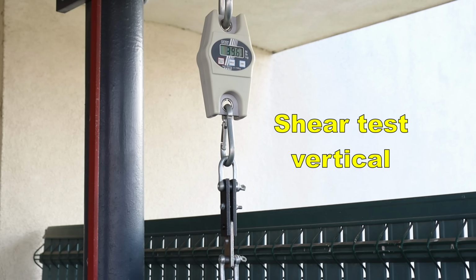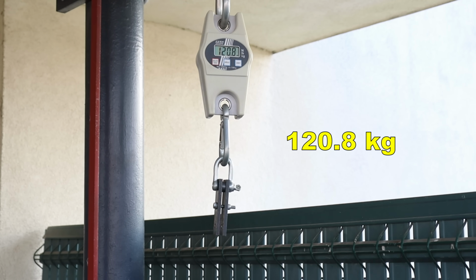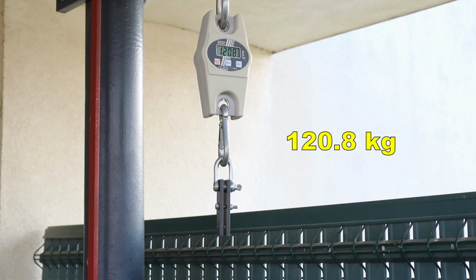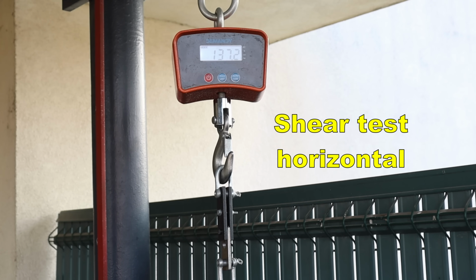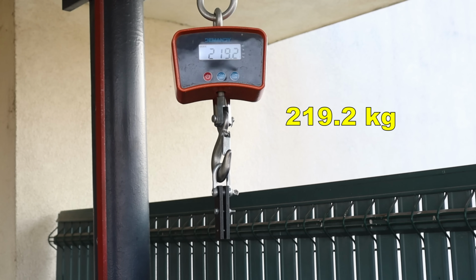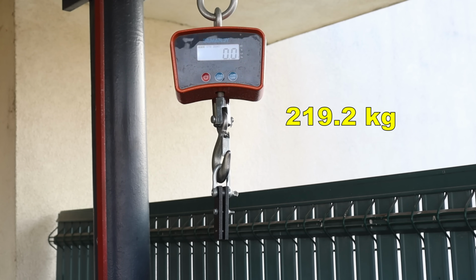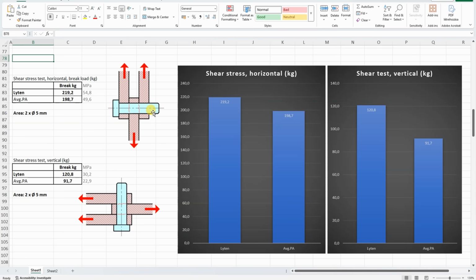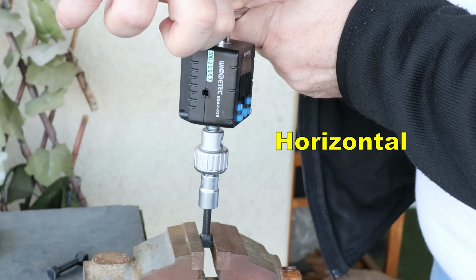Shear test, I'm starting with vertically printed. For the horizontal version, I switched to this stronger crane scale. Printed in horizontal position, fibers always help in this test, and looks like even graphene helps because this is stronger compared to the average PA. Printed in vertical position, the layer adhesion is very important here, and of course the Lyten is noticeably stronger compared to the average PA.